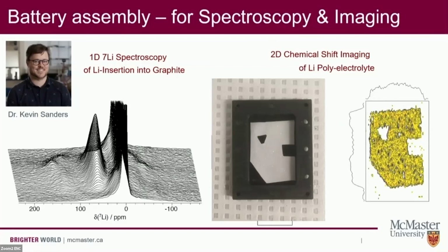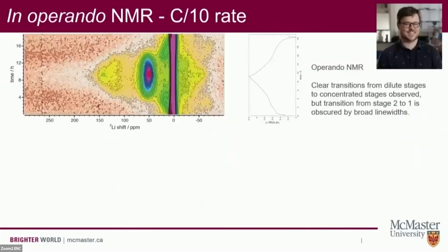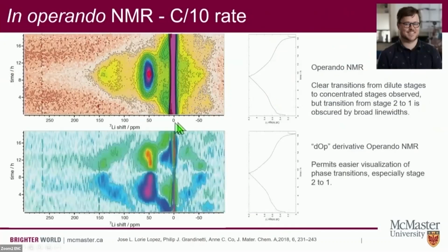And in terms of our collaborations with industrial partners, one of the most important properties of lithium battery chemistry is when does the lithium plating occur? And it turns out that this device is really well suited to measure that. If we insert lithium into graphite at a very gentle rate, we can see the contour plot now is mapping out the spectroscopy of the evolution of the peaks. Kevin is a graduate of Phil Grandinetti's group where he did his master's. So he talked to Phil and helped us to implement the DOP, derivative operando strategy, that allows us to take the derivative of the contour map and therefore highlight where the changes are happening as we insert and then de-insert lithium from this graphite cell.